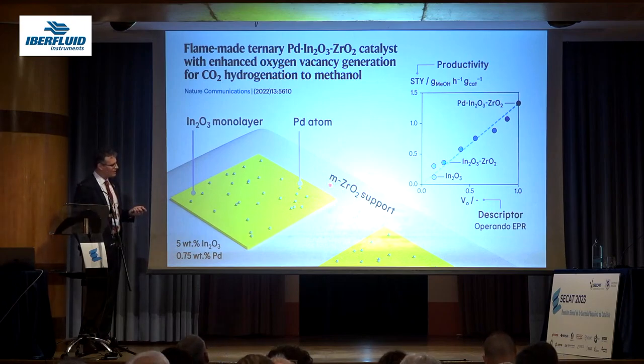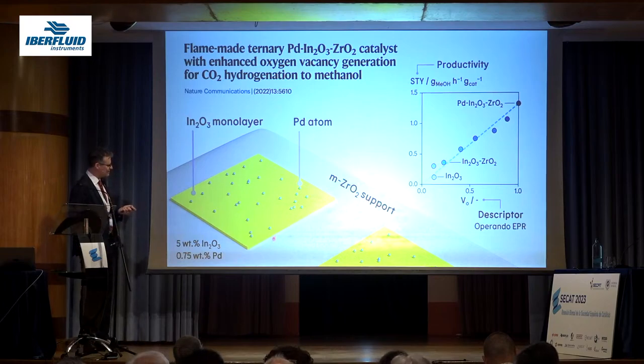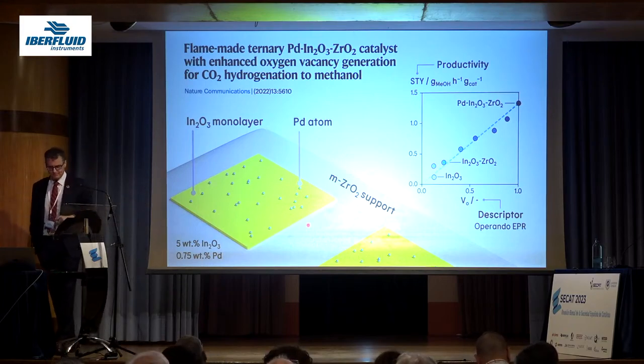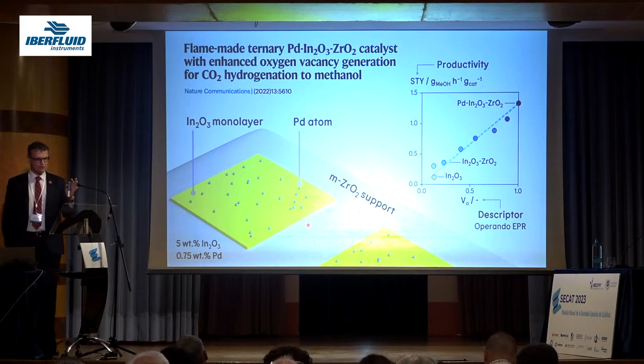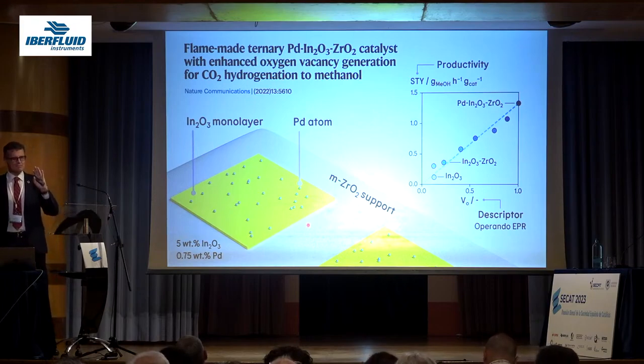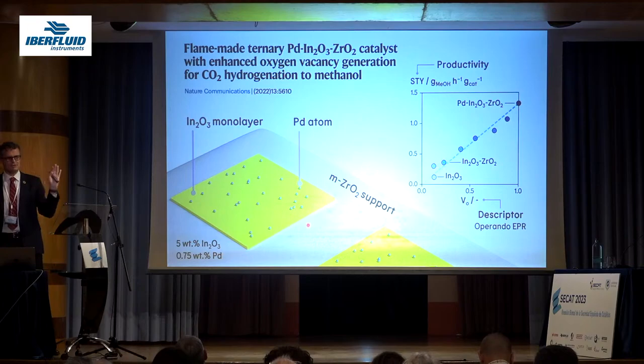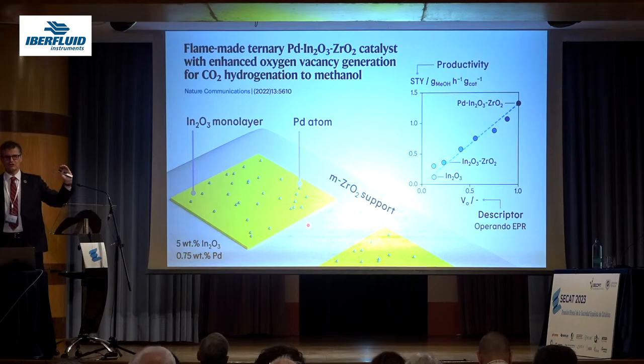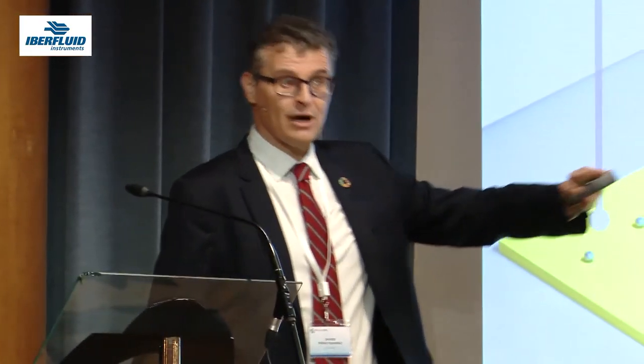You need to have a monoclinic zirconia as a carrier, because monoclinic zirconia also stabilizes these very highly dispersed monolayers of indium oxide. Monoclinic zirconia and indium oxide do not have exactly the same crystal structure, but pretty similar, so there is some kind of dislocated epitaxial growth that actually fosters the creation of these films. And that means when you have these films, the density of vacancies increases. Vacancies are the active sites, so you want to have as many as possible.